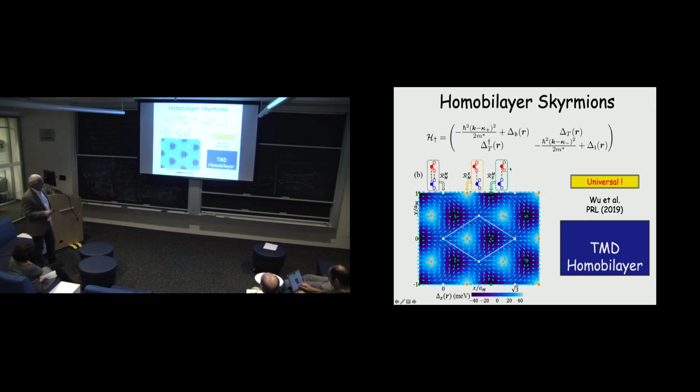The other thing that's plotted here is the tunneling amplitude from one layer to the other, which also varies in position and has a pattern that's dictated mostly by symmetry. Tunneling amplitude, of course, is a complex number, and it's indicated here by these arrows. Length and direction are the magnitude and phase of this complex number.